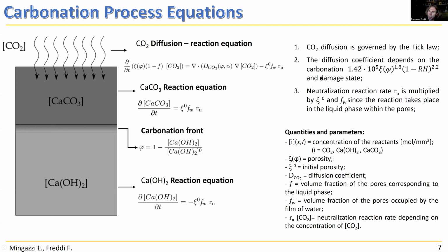The diffusion coefficient is a function of the relative humidity and the porosity of the concrete, but also of the damage state. So where a crack is fully evolved, I assume the diffusion is very, very rapid. After that, there is also the reaction rate. This is a function of the concentration of the CO2. Two reaction equations are considered to determine the concentration of the calcium carbonate and the calcium hydroxide. And also, it is possible to determine, starting from the concentration of the calcium hydroxide, the position of the carbonation front. I think I have no time for many details.